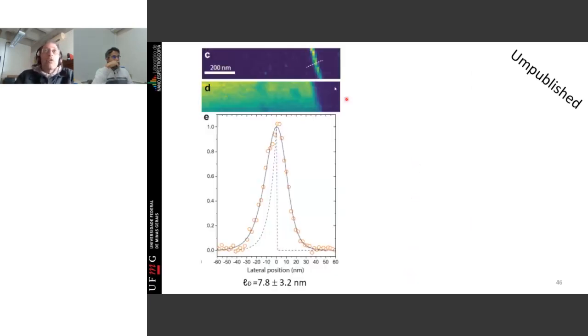Okay, now I can go back to the situation that I started with in the beginning and look at how the intensity goes up and decays when I cross the graphene edge. And when I make the convolution of this with this donut illumination, I know that the emission from the edge is 0 when you are outside graphene. It's maximum when you are at the edge, and then it decays almost exponentially when you go off the graphene. And if you remember, at the beginning I said the green area of graphene is where the defect exists. What we are imaging here directly is that green area from the beginning.